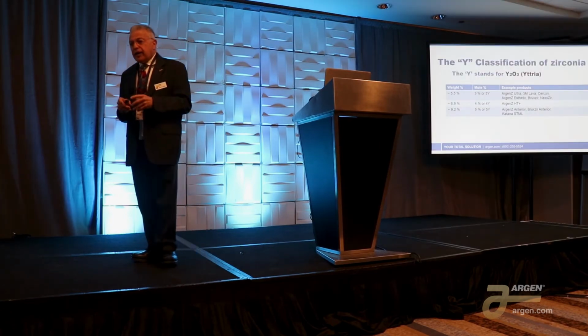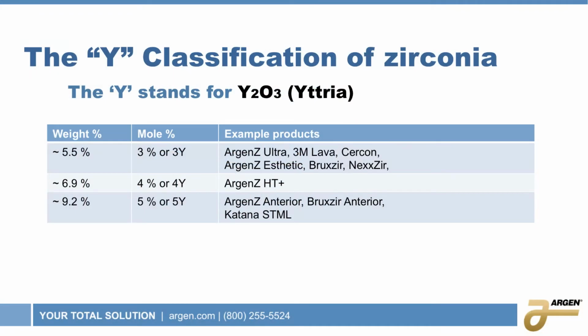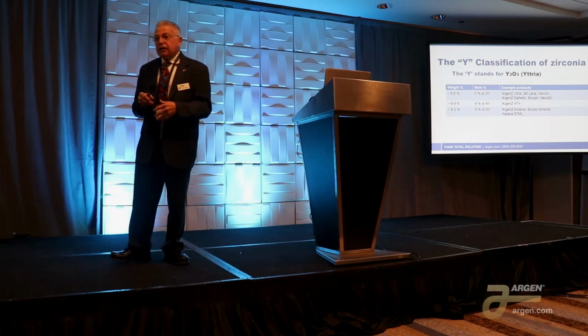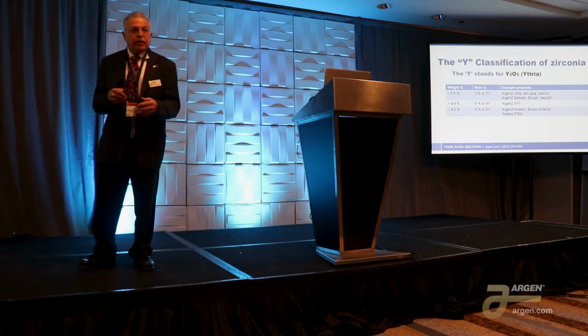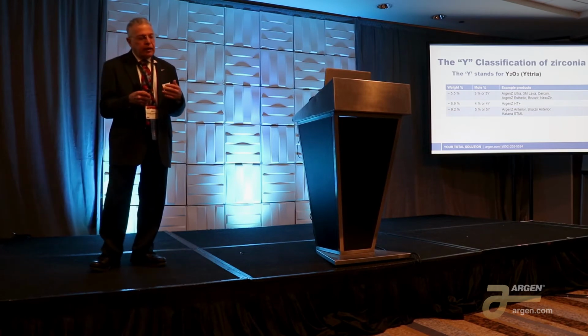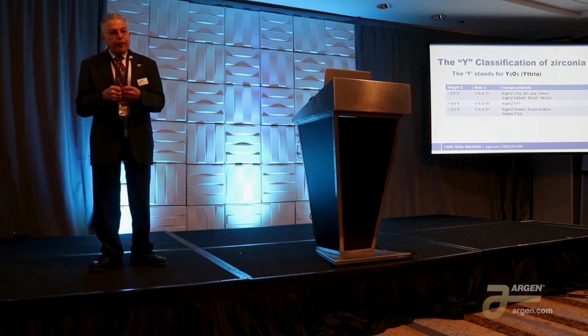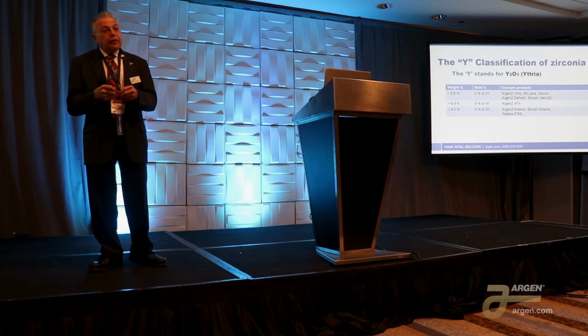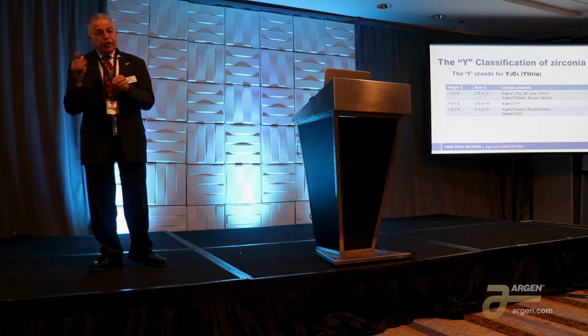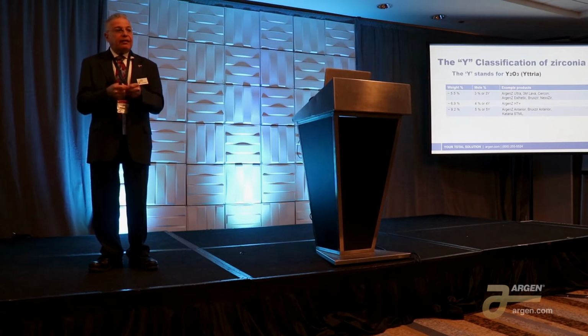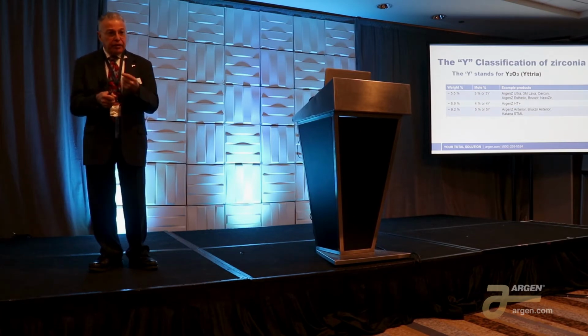Now, this Y classification of zirconia came about from some lectures given by Rella and Gordon Christensen. They said specifically that there was a 3Y zirconia and a 5Y zirconia, and that the 5Y zirconia, in their testing, had some fractures where the 3Y did not. The fractures they were referring to were not fractures in the mouth, but fractures at the dental operatory when the dentist was contouring or adjusting a contact on the zirconia, and we're going to see some of those.